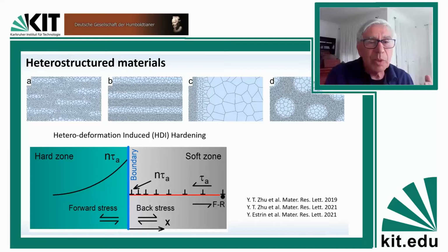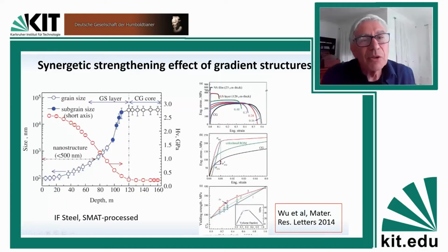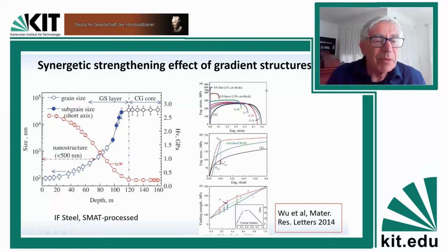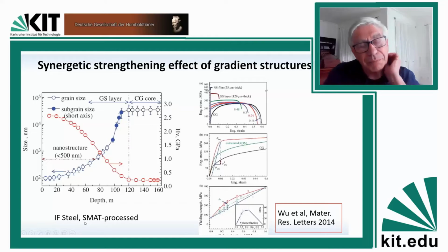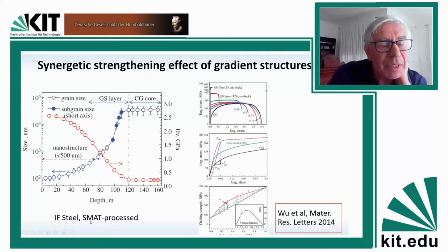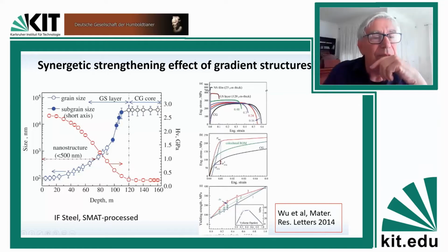So in this controlled way, several groups have designed techniques to improve the properties by bombarding the surface of the material with small particles, the so-called SMAT process. This is surface mechanical attrition treatment. That's the acronym that stands for that. And at the surface of the specimen, you produce a hard layer with the grain size of, say, 100 nanometers. In the core of the material, you have the initial coarse structure, say at micrometer scale. And then there's a gradient layer, a transition between this layer and this layer. The hardness of the material varies, of course.